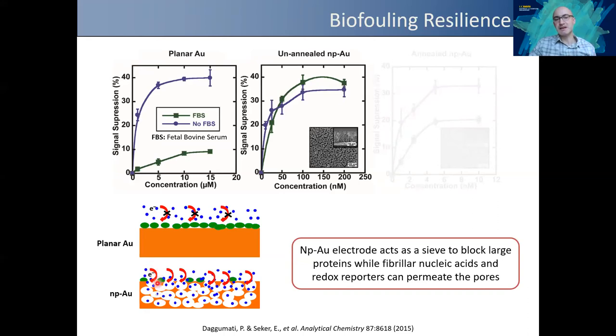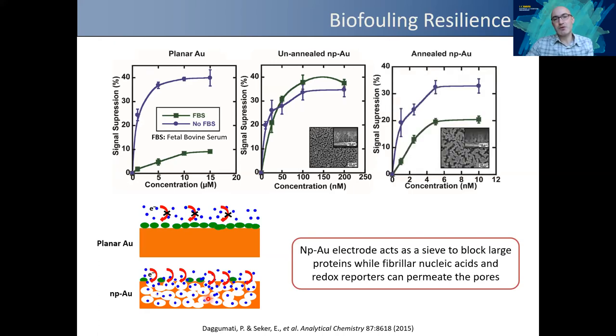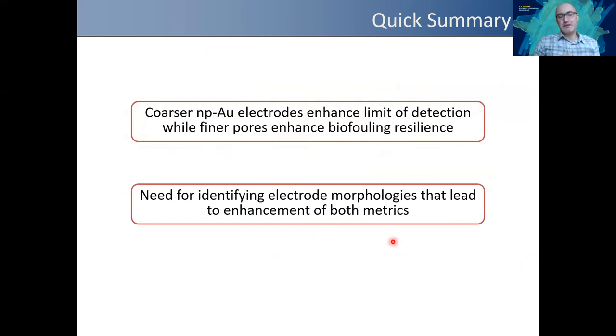So small molecules like methylene blue or fibrillary nucleic acids can still permeate into these pristine, deeper surfaces where you can have electrochemical detection. We tested the hypothesis by coarsening the electrodes, and you can see the effect begins to get lost, because now proteins can permeate deeper and foul the deeper surfaces as well. So now you can see that we want coarser pores for better transport, hence limit of detection, but we want finer pores to enhance the biofouling resilience. So it's a typical engineering trade-off problem.